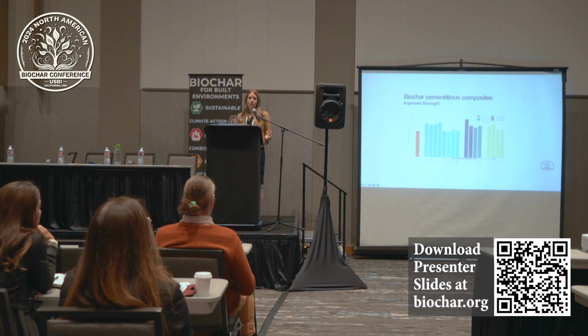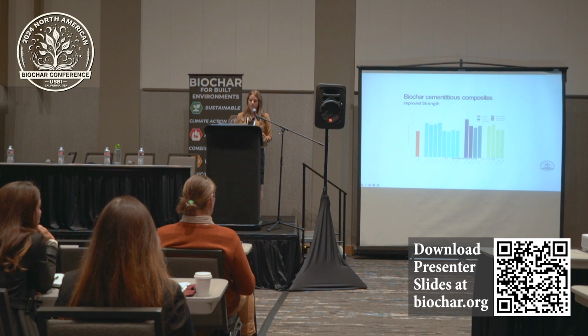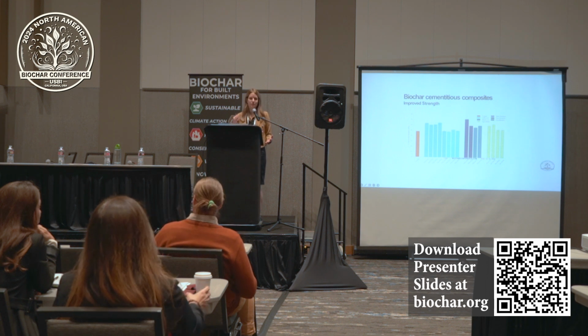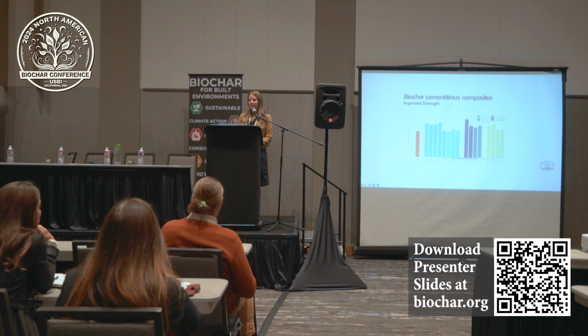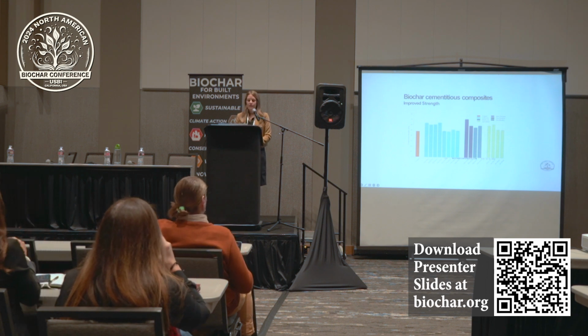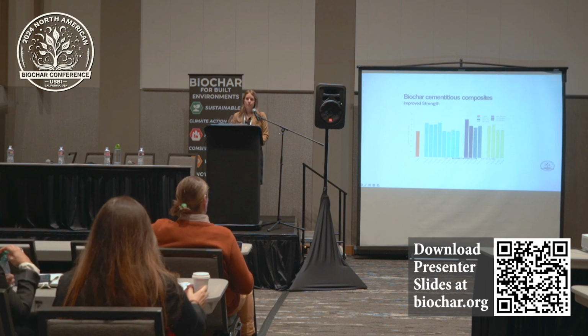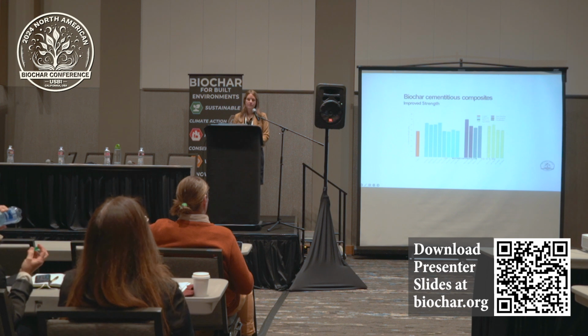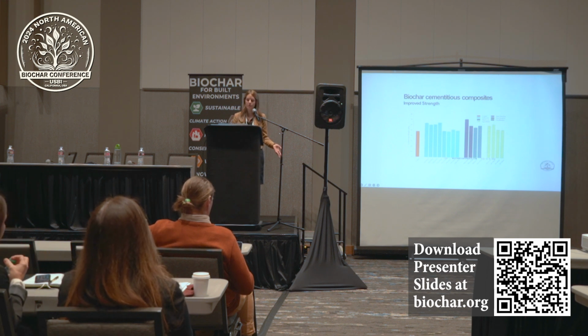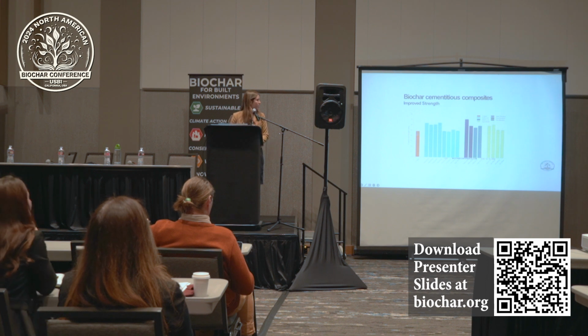So we've looked at a pretty broad range of biochars. We have shown 16 here. We are always looking at more, so we kind of just cut this off eventually. But what we have found is that compared to our control sample, all of the biochars we've tested actually improve strength or keep it the same. So most of them, as you can see, improve the strength compared to our control, which is the sample here.